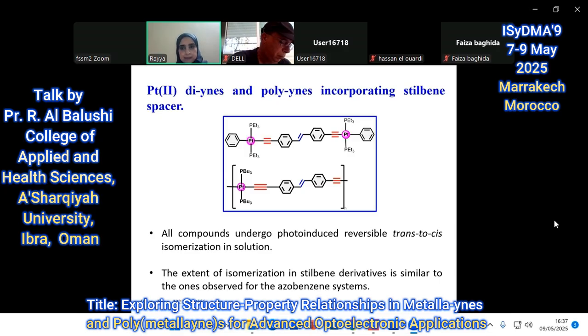So we extended this. While I was working on it, we received a comment that maybe the issue is having those N groups there in the azobenzene. So we changed them. Instead of the azobenzene, we replaced them with stilbene. And we found similar observations: yes, there is photoisomerization, but it is not as fast, so we couldn't get a very good photoswitch with this platinum unit there. Even in the azobenzene, the photoisomerization was somehow better, but to some extent they are similar.